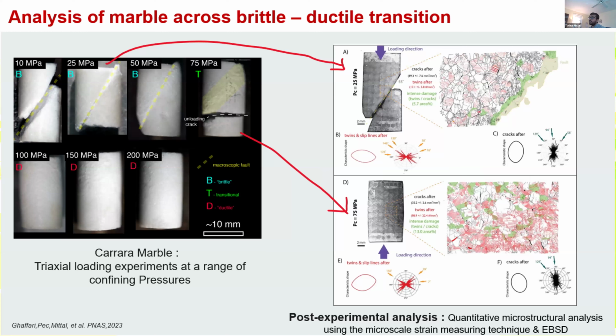And we know that these span the right regimes not only by looking at the macroscopic shape of the samples, but we've also done some EBSD work on a couple of these samples. We can see that you go from more crack-dominated in the brittle regime to more twin-dominated, which is more crystal plastic dominated, as you go to higher pressures. So we know this experiment set has the diversity in deformation behavior that we want to test this method across. We want enough diversity in our experiment set that we can actually test the conjecture that it works across regimes rather than in a very specific regime.